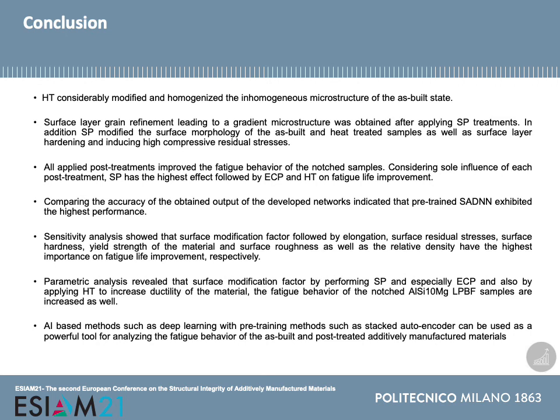All applied post-treatments improve the fatigue behavior of the notched samples, but the highest fatigue improvement occurred by using the hybrid post-treatments of heat treatment, shot peening, and electrochemical polishing together, respectively. Considering the sole influence of each post-treatment, shot peening has the highest effect, followed by ECP and heat treatment on fatigue life improvement.